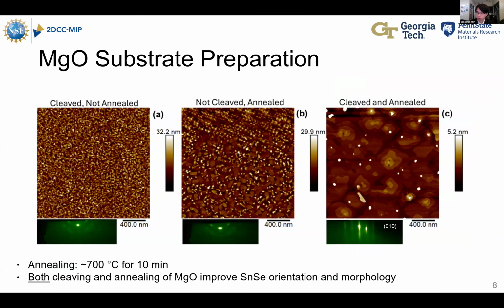Cleaving our substrate is when we split the substrate in half so we can grow on the inner surface. Growing on this interface gives us a cleaner interface. So we potentially have a better lattice match, and we may be able to avoid some of those surface hydroxides and carbonates that will readily adhere to MgO.